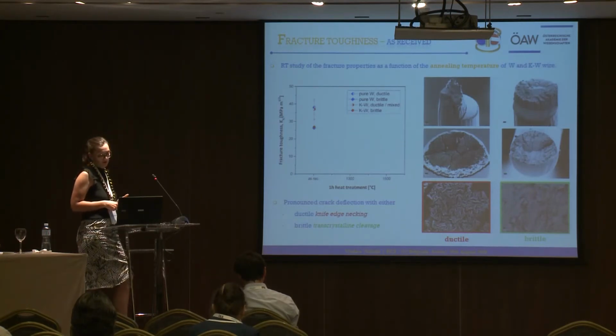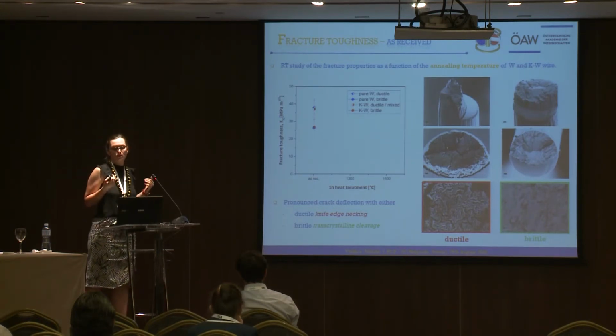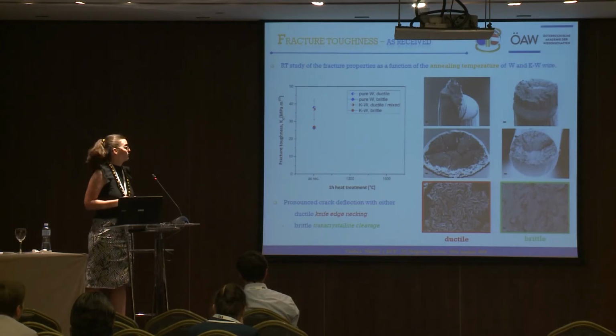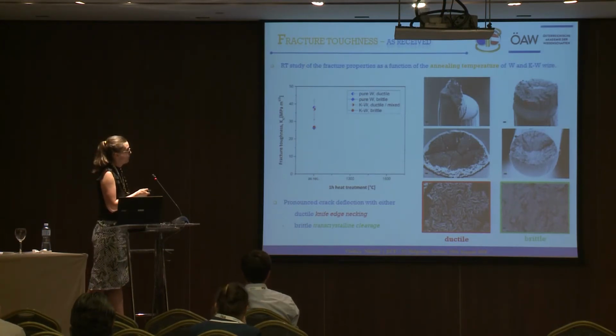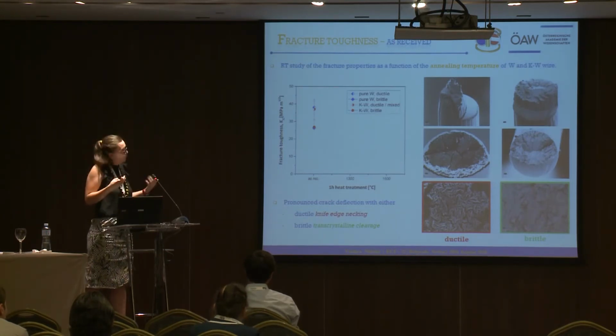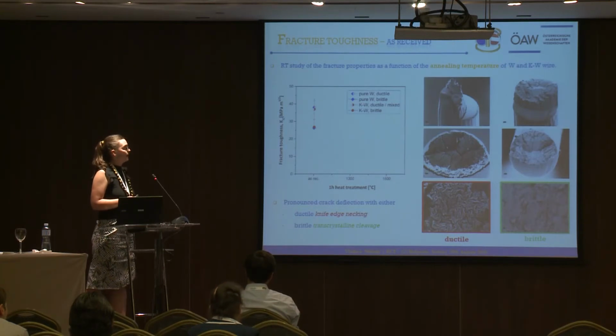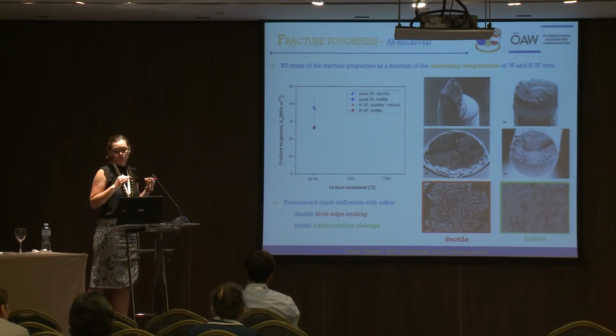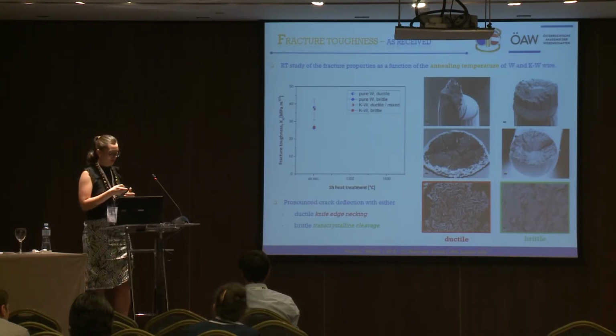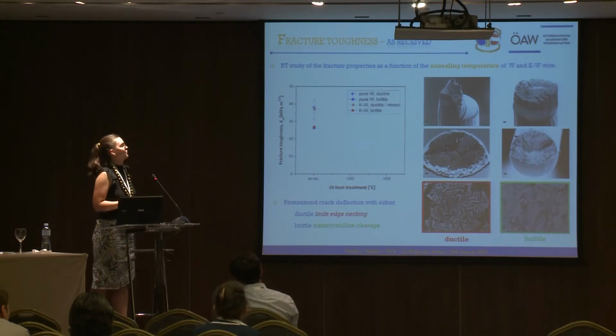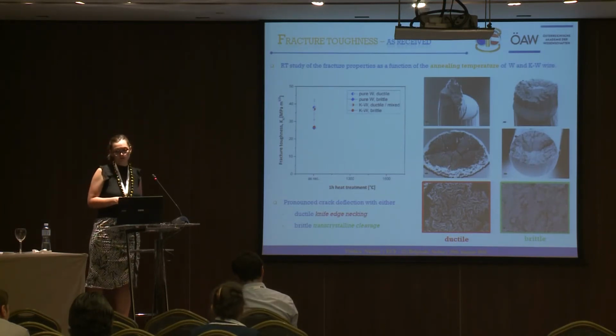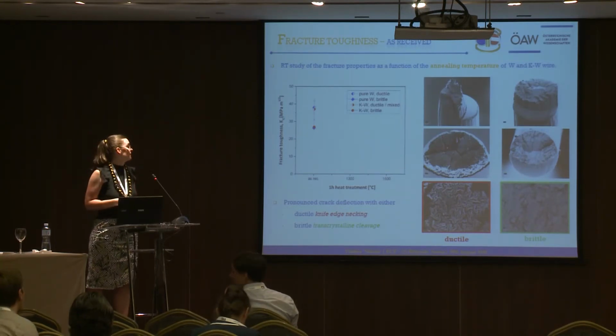And the second very important aspect is that in both of the cases, both ductile or brittle appearance, there is a very large crack deflection happening at the beginning of the fracture process, which you can see nicely in both of them, as this step. So the designated mode 1, which we want to accomplish, is not really happening. So at the beginning, the crack deviates, and it takes the path along the grain boundaries, along these elongated grains, which is a direct indication that we have a very strong anisotropy of our fracture properties.